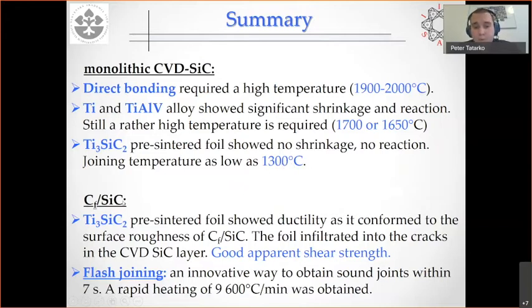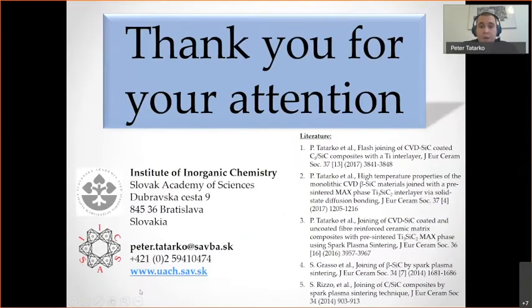In the case of the composite, I would like to just point out the ductility of the MAX phase, which can conform very well because the surface of the composite is very rough, so the foil can really conform very well, and you can get a nice strength. In terms of flash joining, with very rapid heating and the whole process only 7 seconds, you get a very nice joint. That was all from my side.